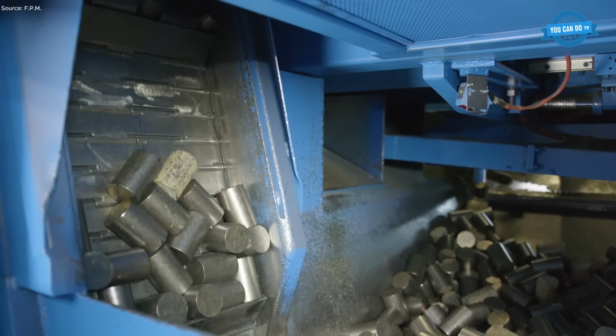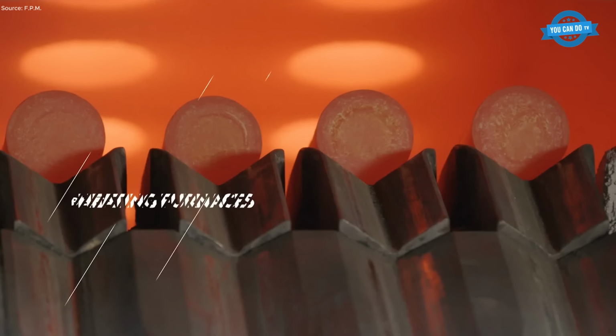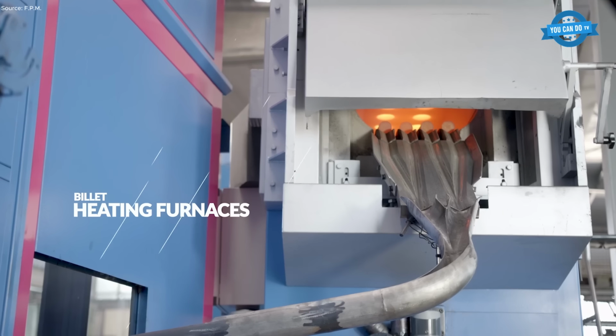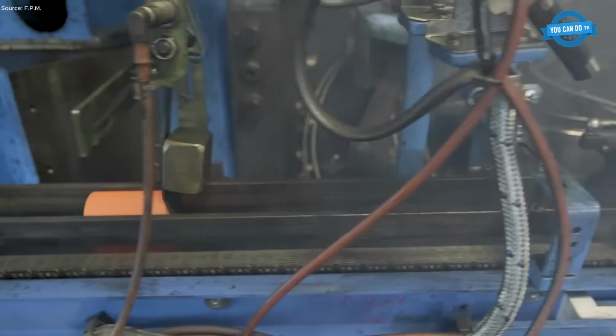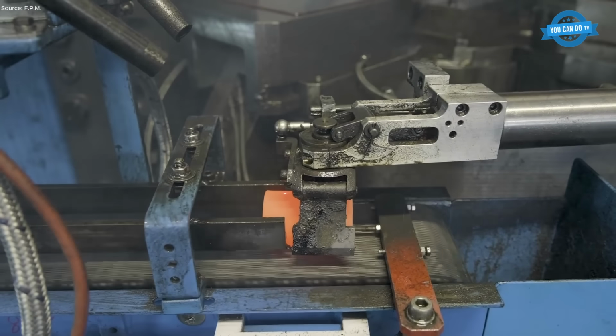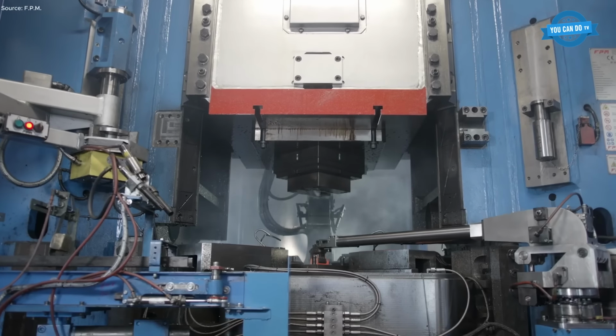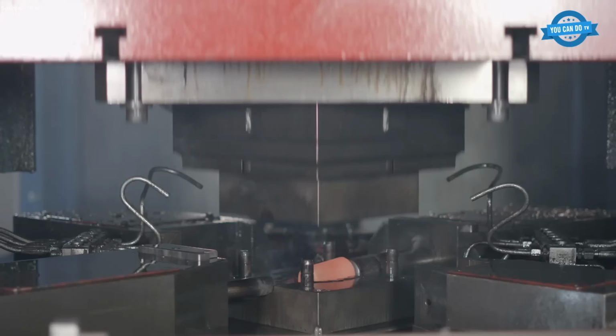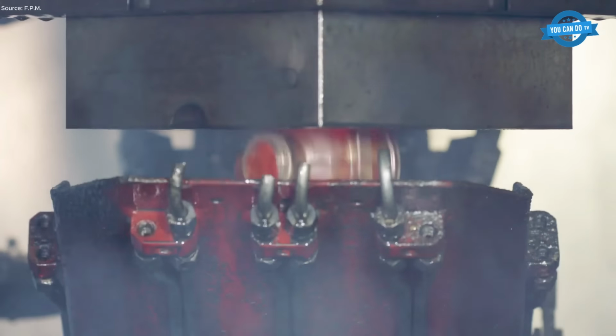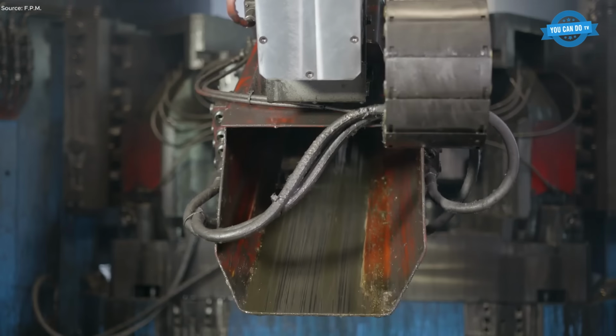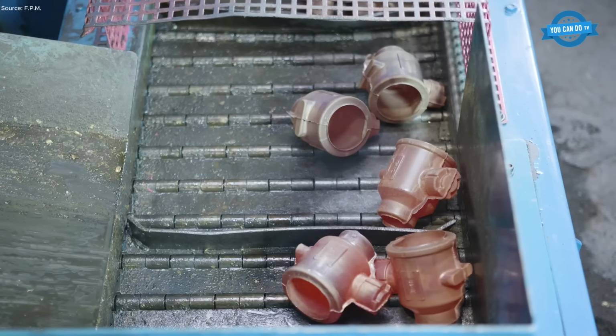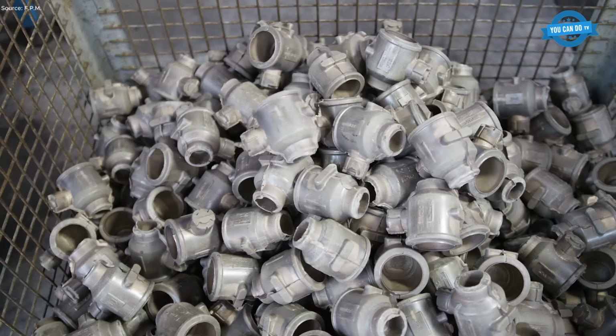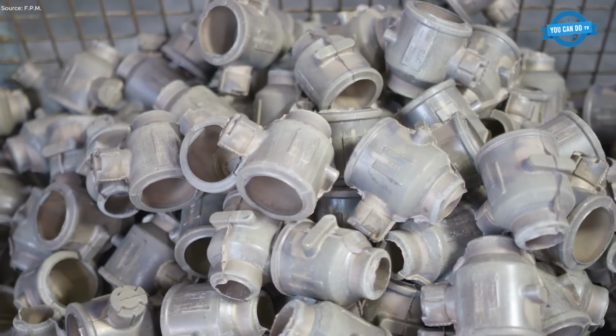Production begins with bar sawing systems that provide precise billet cutting, followed by graphitizing machines that apply controlled lubrication to reduce die wear and improve material flow. Billet heating furnaces ensure uniform temperature distribution, a critical factor for consistent deformation behavior during forging. Forming operations are carried out using mechanical forging presses and friction screw presses, selected according to material type, part geometry, and required forming energy.